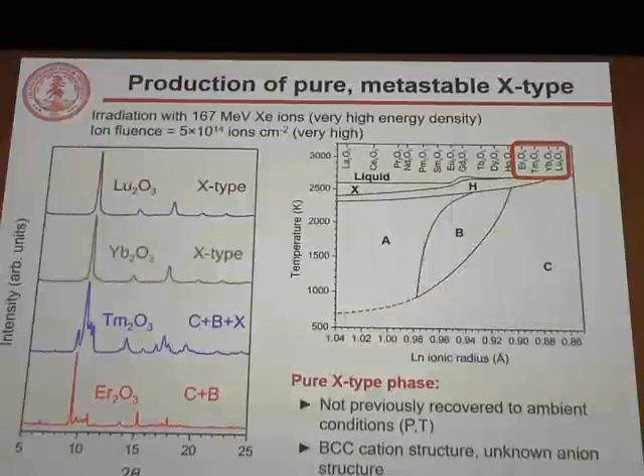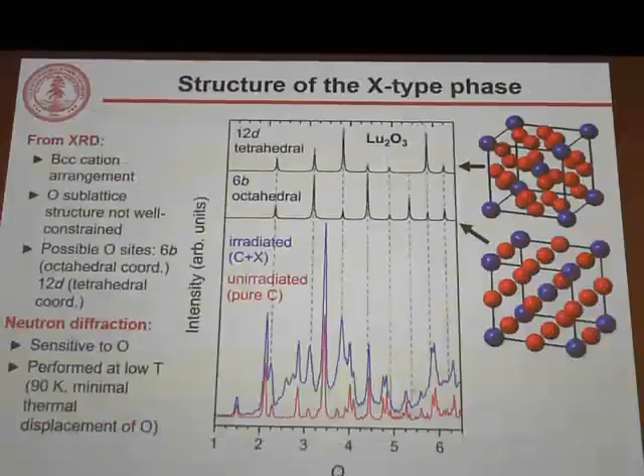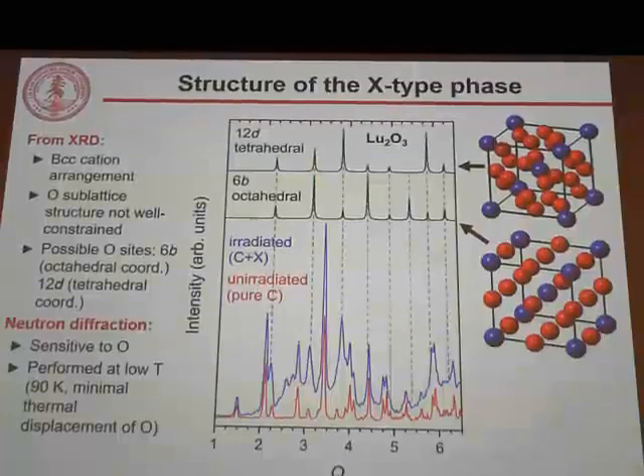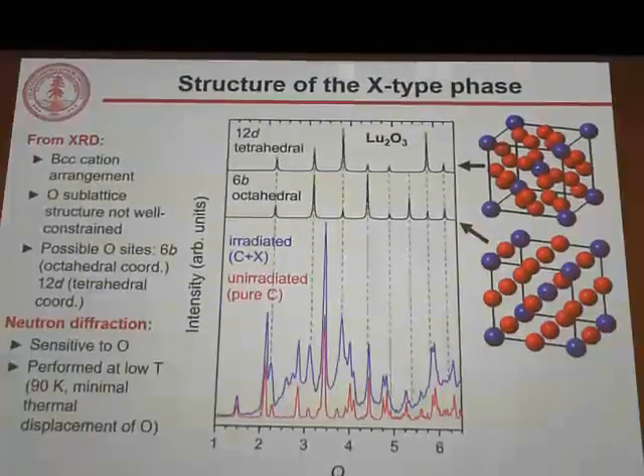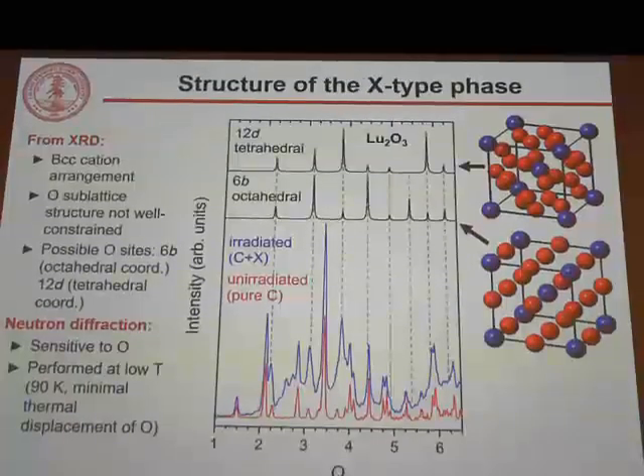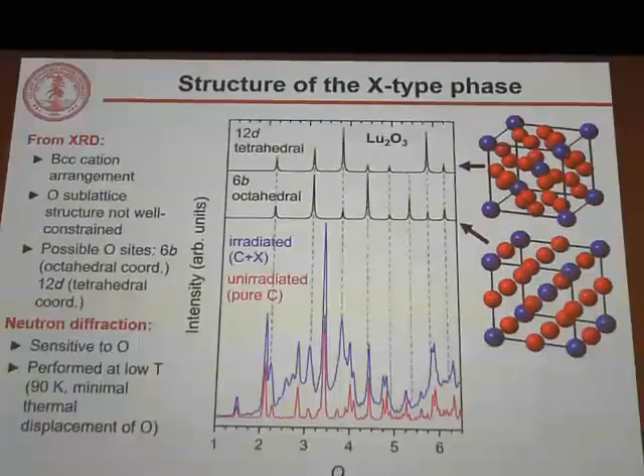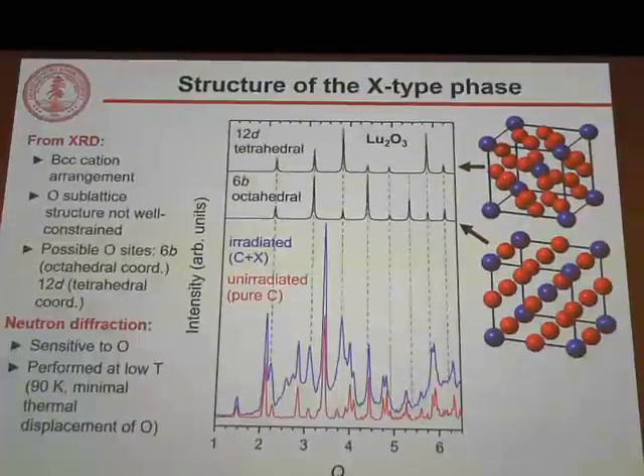We know that it has a body-centered cubic cation sublattice, but the anion sublattice was previously unknown because it could only be formed at very high temperatures. It couldn't be easily characterized. We performed neutron scattering experiments to determine the positions of oxygen in the unit cell of this material. Now, from the known cation structure, which we know from XRD, there are two possible sites for oxygen, one octahedral site and one tetrahedral site.